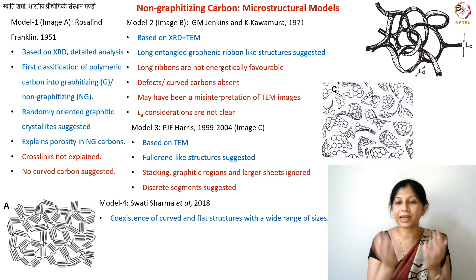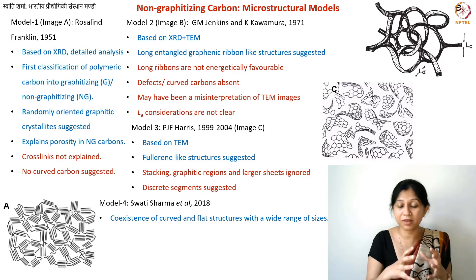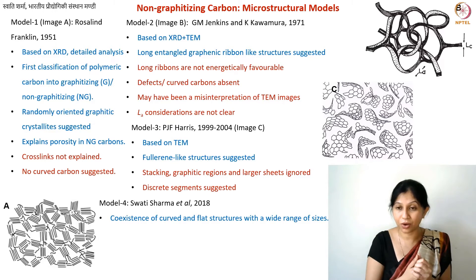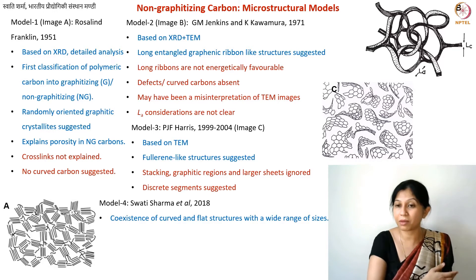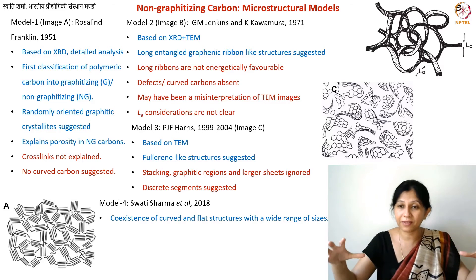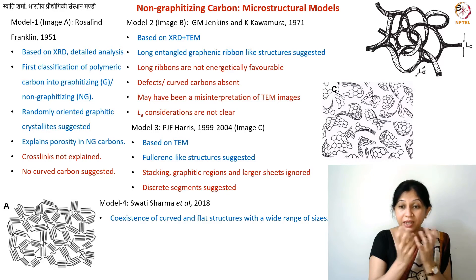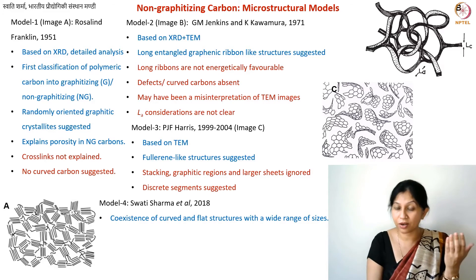This substantiates previous models that yes, we have curved carbon structures — but this is the first time we also saw not just curved carbons but actual fullerenes. Interestingly, there are curved carbon flakes and sheets of very different sizes — some just a few angstroms, some several nanometers. There is a coexistence of larger graphene-like sheets and very small graphene-like disks, and some completely closed spherical structures. Since we only see a 2D projection, we cannot easily differentiate a circle from a sphere.